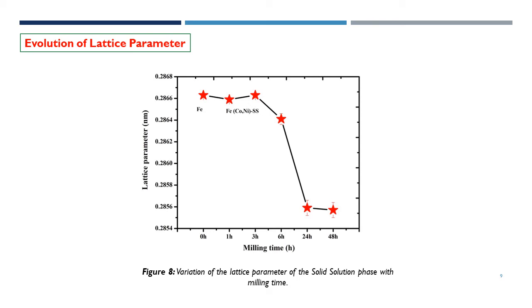The decrease in lattice parameter between 6 and 48 hours can be explained by the high diffusivity of cobalt and nickel through the disordered iron matrix. In addition, this reduction may be attributed to particle compression, which is due to the presence of compressive stress fields in the non-equilibrium boundaries within the microcrystals.